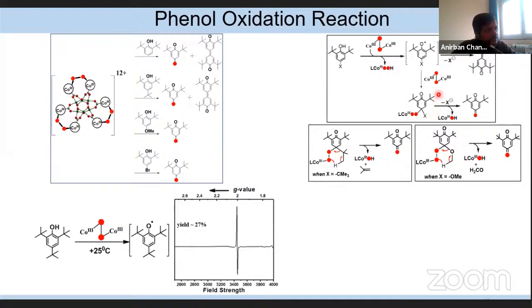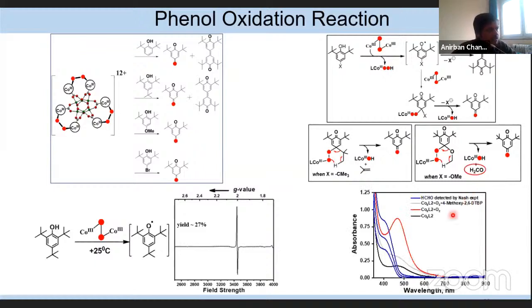However, for the formation of the 1,4-benzoquinone, there are two possible mechanisms. If we use some kind of methoxy group with oxygen, then we can see the formation of the formaldehyde, and if we use some alkyl group such as tertiary butyl, then isobutylene should be released. But since the reaction is stoichiometric and the amount of isobutylene formed is really small, I can't detect it in GC. However, I am successfully able to detect the formaldehyde via the Nash experiment.